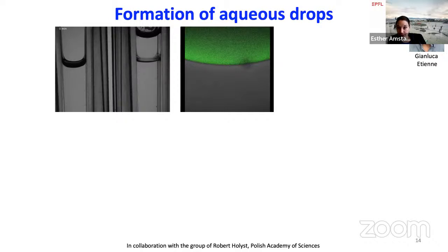There were a couple of iterations going on. Initially I thought we could suppress that by tuning the surfactant composition, but it turned out that this was just not the right way to go. And so I asked the student to make a very simple experiment: to take this oil with the surfactant, once in contact with air and once in contact with the aqueous phase. If you look closely, what we saw is that at this interface you have increasingly more objects that start to scatter light. But objects that scatter light must have a dimension similar to the wavelength of optical light, so 100 nanometers, much, much larger than any micelle can be. So in our systems, the formation of micelles just didn't really add up to what we see.